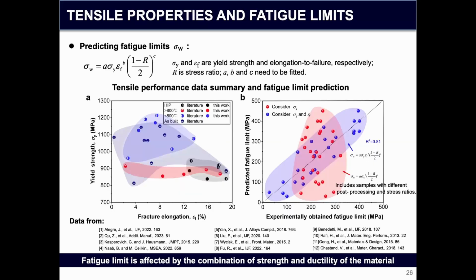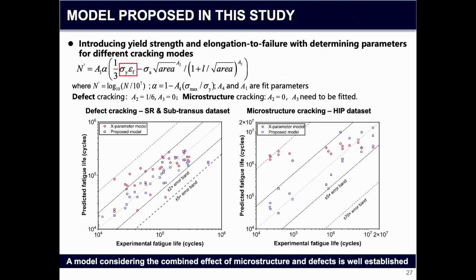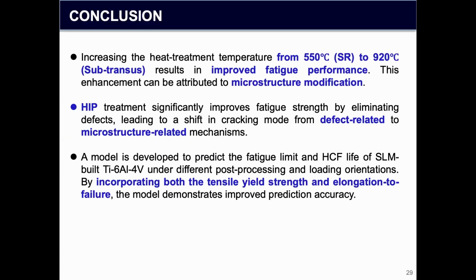So we use very simple tensile properties like the fracture elongation and yield strength, because we find the fatigue limit is very much related to these 2 properties. So this is our model, and we actually reduced the error very much. And this is the conclusion.